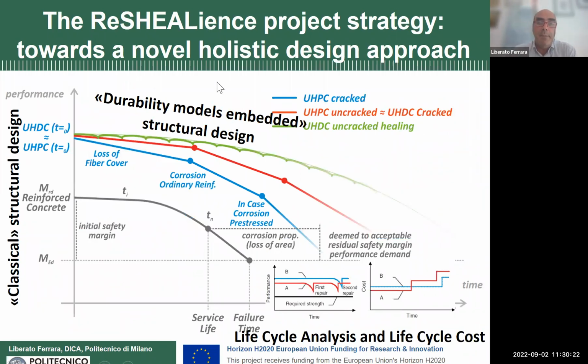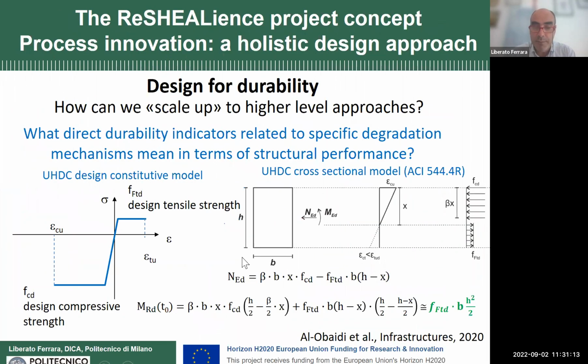So we tried to develop this concept map, saying, okay, if I am a civil engineer and I have to design a structure, could be a wall, could be a slab, could be any other kind of structure, I have in mind in the beginning a structural mechanical performance, could be the resistant bending moment or any other kind of structural capacity indicator. And I design with a certain initial safety margin, but I do know that because of aggression and degradation, this level of structural performance will decay over time up to a certain point. First, there is a mild decay. This is a classical model for corrosion of reinforcement. Until the chlorides or the aggression penetration reaches the cover, you have a mild degradation, but when it reaches the reinforcement, the corrosion starts, so you have a very, very rapid decay.